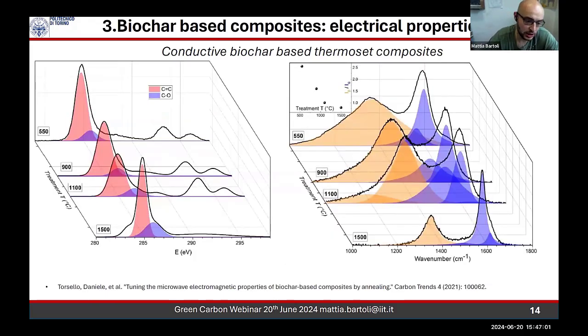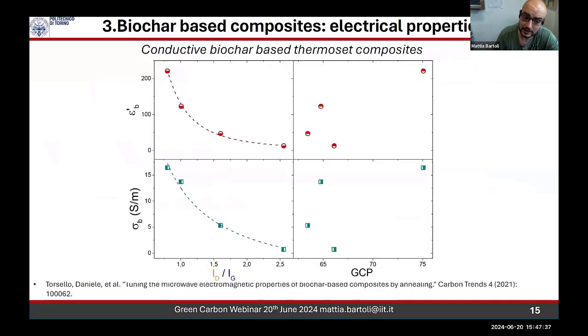And this is an objection that I hear a lot. If you are not running the whole process in a proper inert atmosphere, and you are running a combustion process, the oxygen functionality remaining in your biochar is affecting the conductivity, and the answer is no. Here you can see some XPS and Raman analysis of the carbon treated in a proper auto-combustion system. And you can see that even if oxygen is present in all of them, the conduction is following the same path that was expected. It means that basically you can have oxygen while preserving the conductivity, and combine the two things, so you can have a solid solution for the production of biochar treated at very high temperature without compromising too much on the cost of the material.